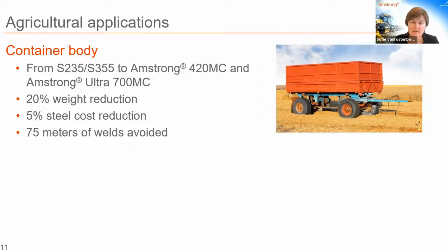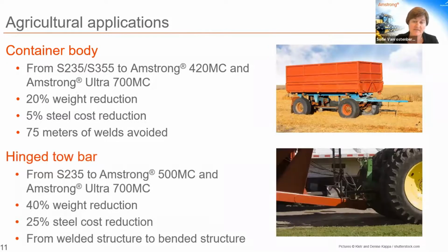Another example, in the field of agricultural applications, is the hinged tow bar, which is in fact the part which makes the connection between the tipper and the tractor. Here the S235 grade was replaced by an Armstrong 500 and an Armstrong Ultra 700 grade. And this represented a weight reduction of about 40% and a significant steel cost reduction of 25%.